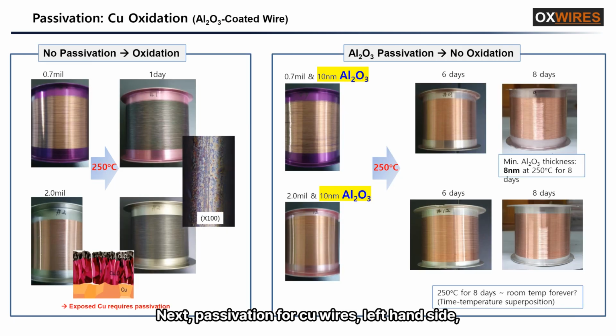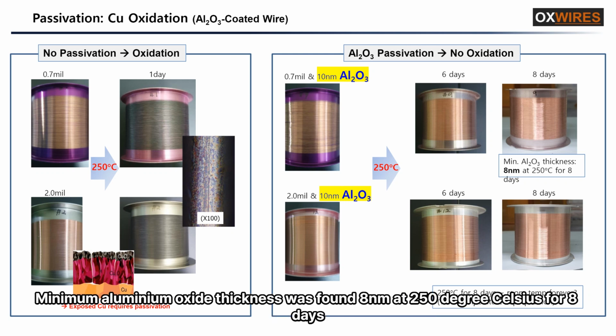Next, passivation for Cu wires, left-hand side. Conventional copper wires, at the end of one day, showed very severe copper oxidation. When we applied aluminium oxide coating, in 8 days we did not observe any color change of the wires. Minimum aluminium oxide thickness was found to be 8 nanometers at 250 degrees Celsius for 8 days.